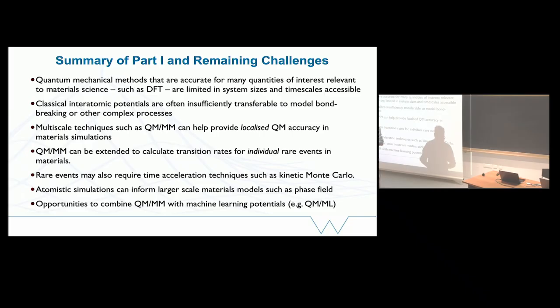So do you mean ionic temperature or electronic temperature? Well, both of them are not 0, I guess, is the right answer. But let me try and explain a bit more. So we're doing a molecular dynamics calculation. The atoms are moving around with the forces that we've taken by mixing together the DFT forces and the classical forces. So they're away from equilibrium. We take that snapshot, and we put it into DFT and evaluate it as a single point calculation. We're not doing dynamics in DFT at all. We're just getting energies and forces from DFT. But the atoms are displaced as they would be at finite temperature.